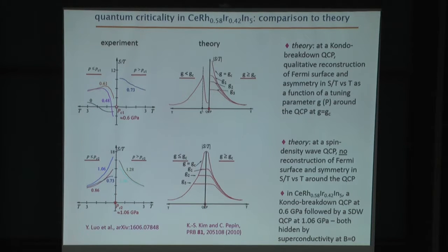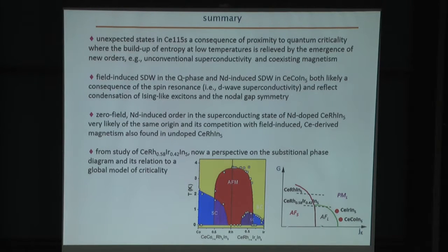On the other hand, at a conventional spin density wave quantum critical point, there is no reconstruction of the Fermi surface. And in this case, as one approaches the quantum critical point with decreasing temperature, the thermopower is essentially symmetric across this T equals 0 phase boundary as a function of the tuning parameter. And again, this is what we find experimentally for pressures about 1.06 GPa, which is where the magnetic transition goes to 0. So just from this comparison of theoretical predictions to experiment, we would imply that there are two qualitatively different types of quantum critical points in this material as a function of pressure. There is first a Kondo breakdown quantum critical point that is followed at a slightly higher pressure by a spin density wave quantum critical point. And both of these quantum critical points are hidden by superconductivity in the absence of an applied field.